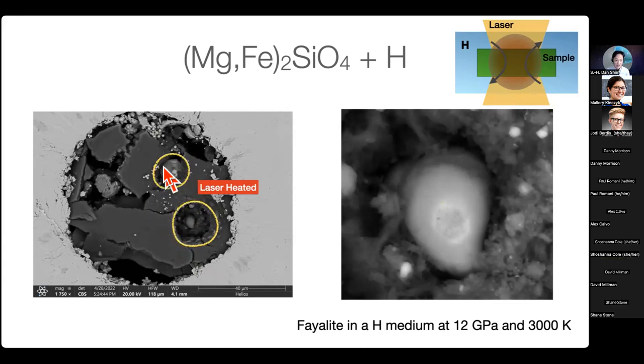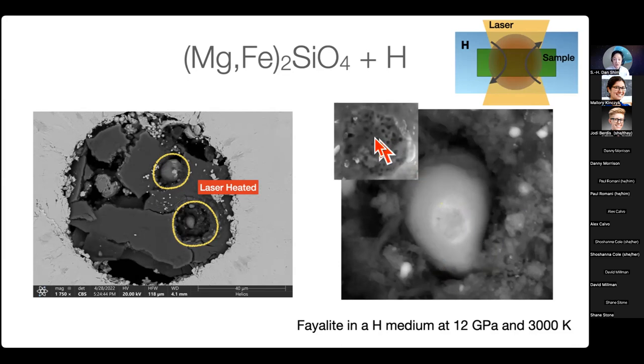If you look at the reacted area, you can recognize the spheres at the center of the heated area. In fact, that sphere, this is a zoom in view of this particular heating spot, is actually metallic iron alloy with silicon and hydrogen. Well, hydrogen doesn't stay in iron alloy when you quench to one bar. So hydrogen escapes from this metal sphere and leaves these little holes. These are nanometer size holes on the surface of the iron sphere. So in some sense, you're looking at the formation of metallic core in a micro scale in this experiment.